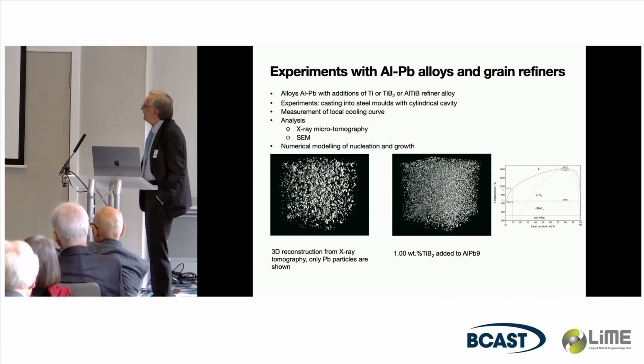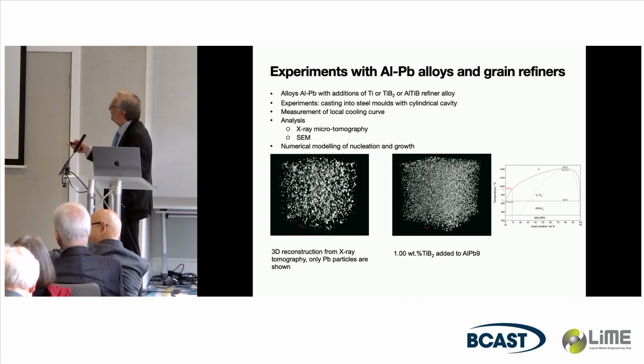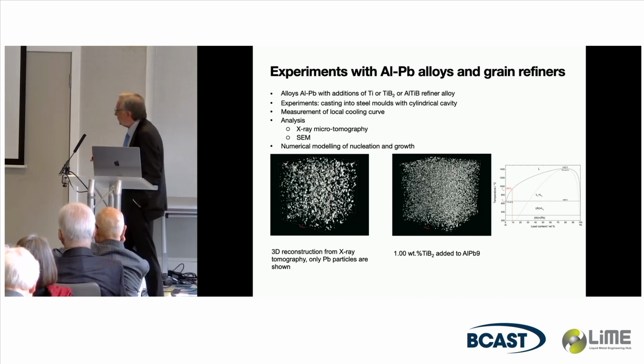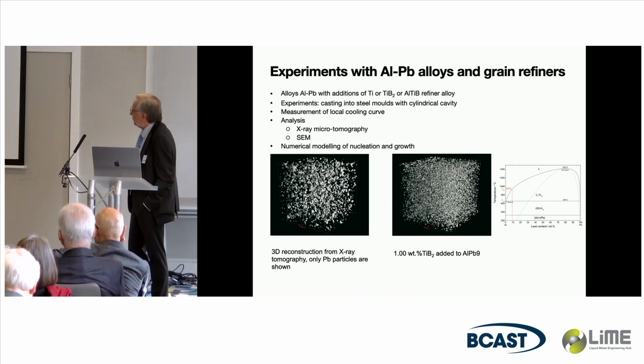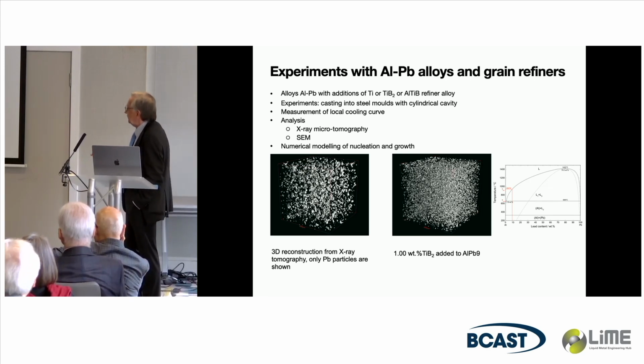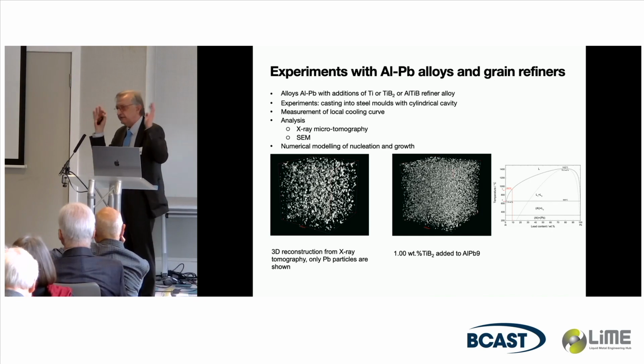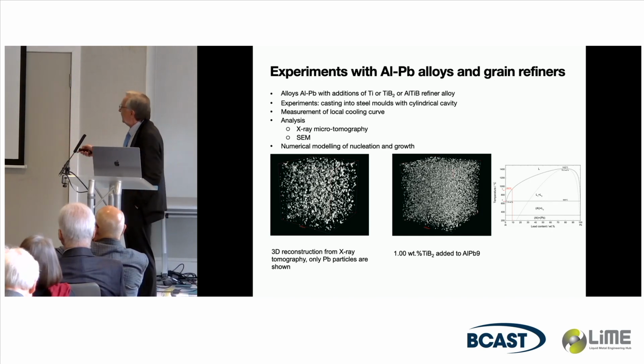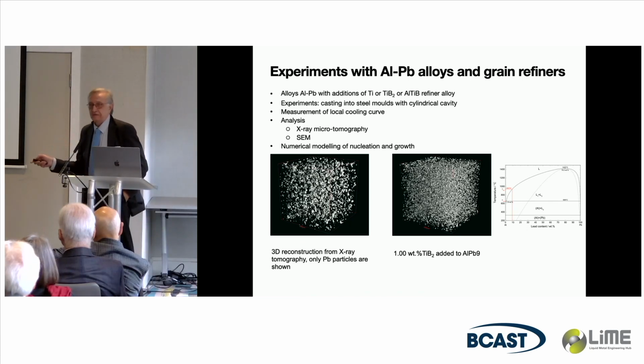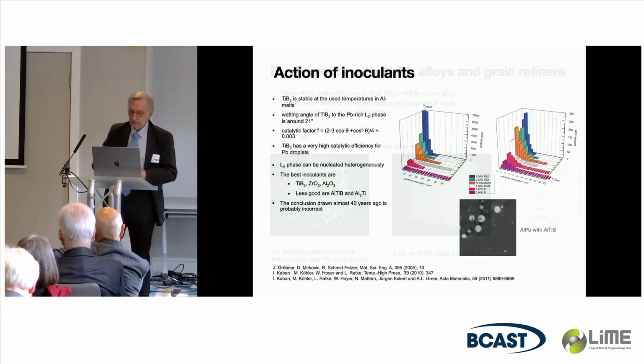Because we made later some wonderful experiments with aluminum lead and added some grain refiners, titanium diboride particles, a classical grain refiner alloy. We did X-ray tomography, and you simply look at this here. This is an X-ray tomograph without any grain refiner. Now we added titanium diboride particles, everything the same, same cooling rate, same sample size, all other parameters the same, and you make X-ray tomography from that, and from here to here you nicely see there are many more particles. So it's definitely something like heterogeneous nucleation.